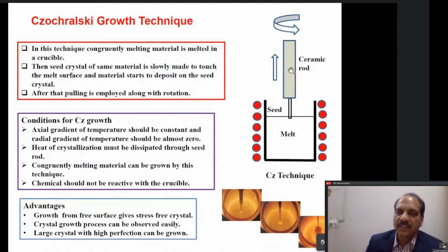So once you touch that seed rod to the melt, you suddenly lift it up also. But you don't let that seed get detached from the surface, and you will see that because of the surface tension, the crystal is still sticking to the melt level. And then you rotate and pull this ceramic rod.